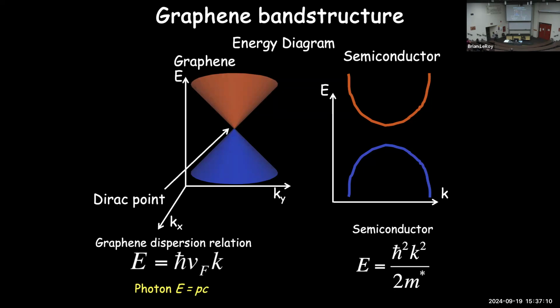k and p are momentum here. And in a photon, the relation is the speed of light, c. In graphene, that relation is the Fermi velocity. And so in this graphene, the charge carriers in the graphene, the electrons, quasiparticles here, are behaving like massless particles that are having a dispersion relation where they have a speed that's 1/300th of the speed of light. And so that gives rise to some interesting new physics in there because of this linear band structure as opposed to the quadratic band structure that is typical in most semiconducting materials. So graphene was the first one to be sort of isolated in 2004.